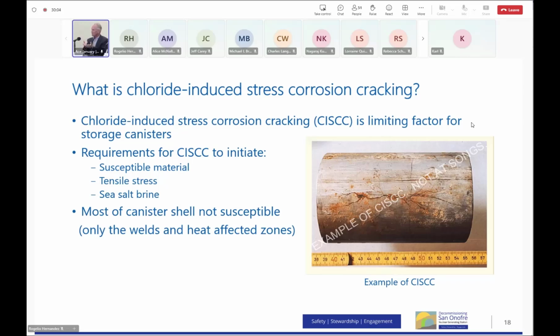So the canisters are made from plates that are rolled into a circle and then welded. They have one long weld down the horizontal. They have one belt line weld around the middle. So those weld areas are the susceptible areas. They have the tensile stresses. And in the Holtec system, we used peening. I don't know if you're familiar with shot peening. Nowadays, instead of shot peening, where you'd fire BBs at it to peen it, we use a laser to hit it with 1 million laser pulses to create a compressive stress layer at least 2 millimeters deep on all our weld areas.